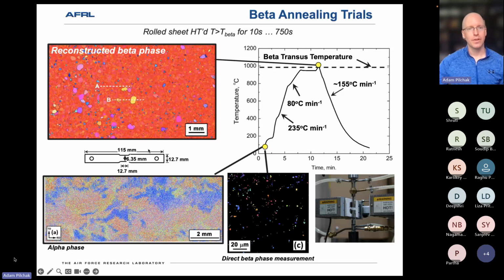So here's an example of one of those experiments we thought were failed, but turned out to be really useful. In that work, we had these flat plate-like specimens, and we were heating them up, holding them just below the beta transus for a couple minutes to stabilize the structure, and then we would flash the sample above the beta transus before cooling at around 155 C per minute. And as I said, we had different times up there ranging from about 10 seconds to 750.